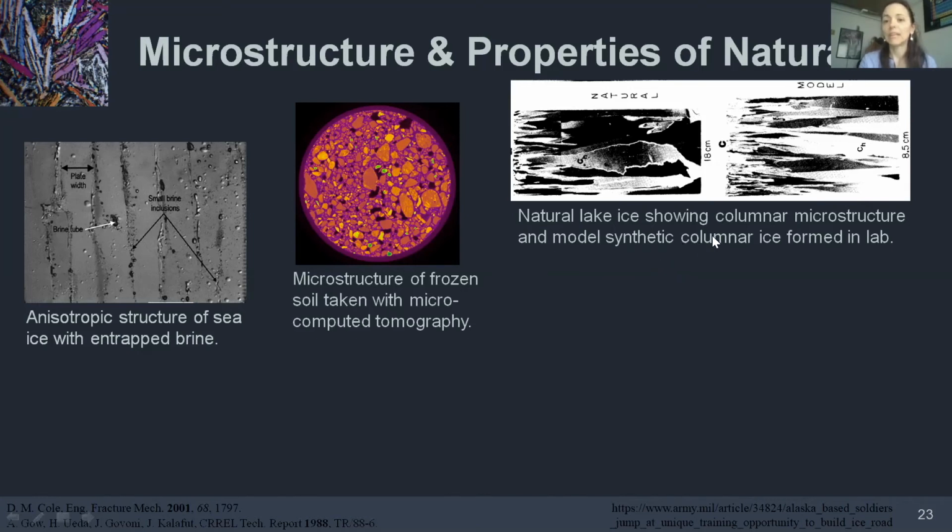Here's some natural lake ice from an old image that Tony Gow actually took, and you see these elongated grains that are characteristic of growing in a temperature gradient. You see how he's denoted this C with a sub H. The C axis is horizontal to the length of this grain. So that's very, very unexpected, and it relates to the formation conditions.